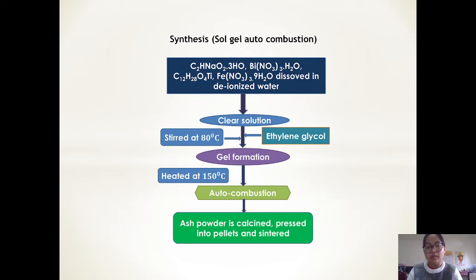The temperature is raised to 150 degrees Celsius, after which autocombustion takes place and an ash powder is formed. The ash powder is ground and calcined at 800 degrees Celsius. The calcined powder was mixed with polyvinyl alcohol and pressed into pellets and finally sintered at 1100 degrees Celsius for measurement.